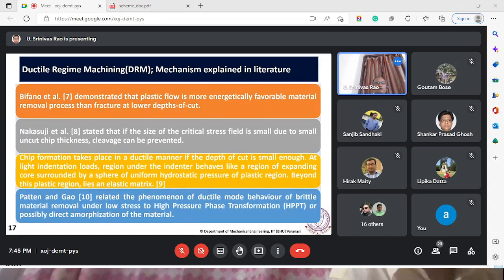So some literature gives some inputs to this. Plastic flow happens more energetically favorable material removal process than fracture at lower depths of cut. If the size of the critical stress field is small due to the small uncut chip thickness, the cleavage can be prevented. Okay. So in all these cases, what is the highlighted point is that we need to control the critical stress field through small uncut chip thickness.